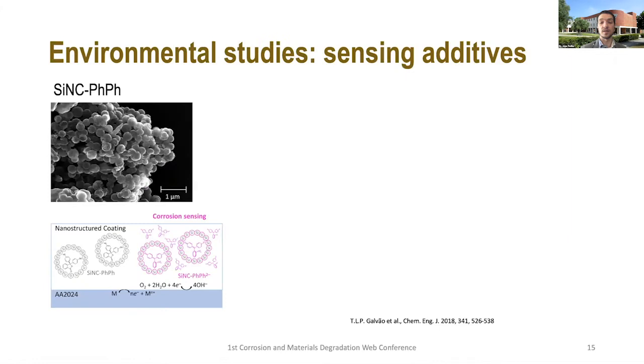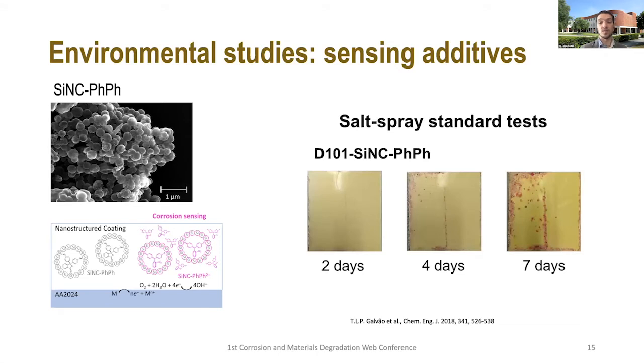Another study was done with additives that we wanted to use to help us detect corrosion, coating degradation or initiation of corrosion processes. One of the systems we developed was silica nanocapsules with phenolphthalein. So we were using a pH indicator to reveal an increase in pH on a coated substrate, and we could see that only the encapsulated form was able to turn color, whereas the free phenolphthalein could not. So there was a deactivation of the phenolphthalein when it was dispersed in the coating.